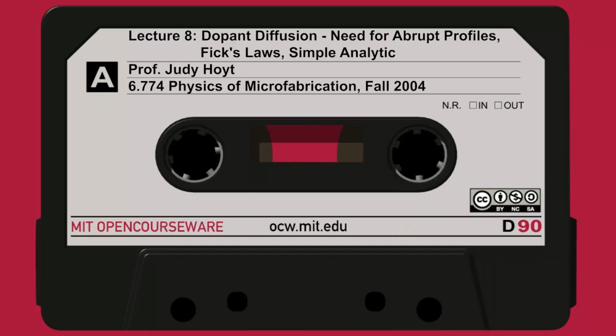Well, there's a relatively simple trick for solving this. If we can assume that there's no dopant loss through evaporation or segregation at the surface, that the dopant is contained in the surface. If there's evaporation, all bets are off, and we have to solve it differently. So we assume that there's no segregation or evaporation. We also assume that the annealing takes place over a long time, so that the initial profile can be reasonably approximated by a delta function compared to the final profile.